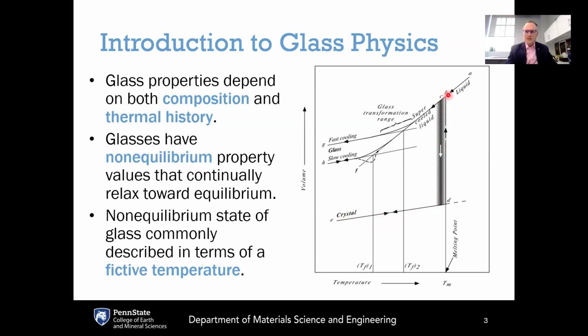Now, crystallization takes time. It takes time for the atoms that are in the disordered liquid configuration to rearrange themselves into a perfect crystal structure. And if you were to take this liquid and cool it so quickly through this gray region where crystallization is likely, you can get what's called a supercooled liquid. A supercooled liquid is just any liquid that is cooled below its normal freezing point.